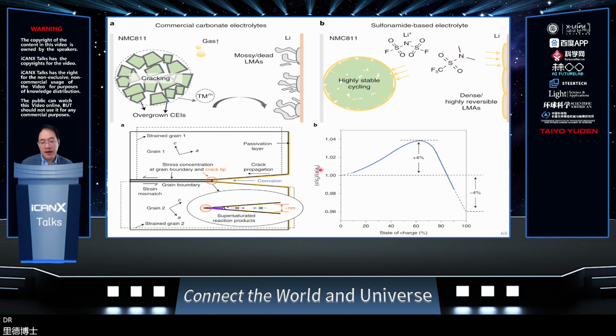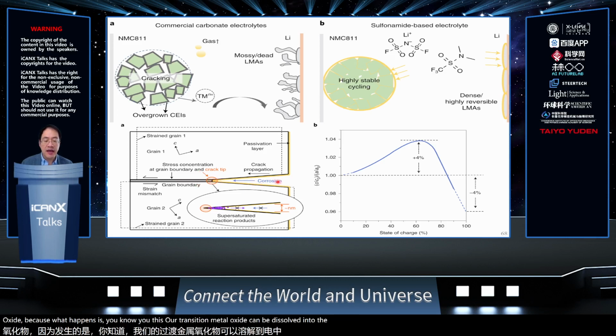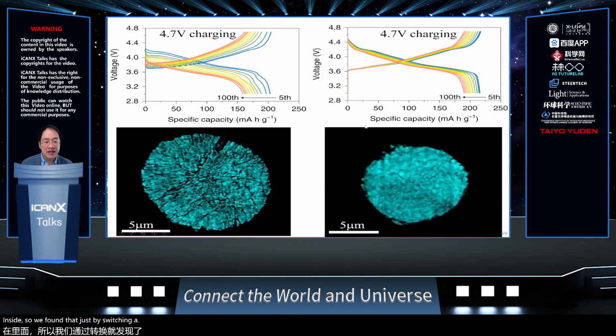Weijiang Xue, that we can greatly reduce the corrosion of the oxide, because what happens is, this transition metal oxide can dissolve into the electrolyte, and so we want to develop an electrolyte which has low solubility of nickel, cobalt, and manganese, but still allows lithium to have significant solubility and transport lithium inside. So we found that just by switching to a different liquid electrolyte, we can greatly reduce the cracking in the system.